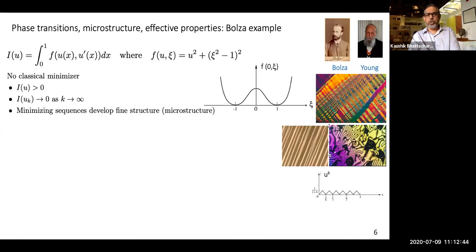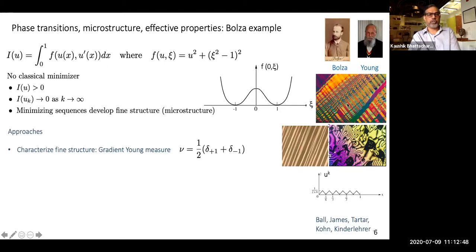And so there are multiple tools you can use, and a lot of them were developed in the context of martensitic phase transitions about 20 to 30 years ago, but we can apply them in many, many different fields. The one is trying to characterize the oscillations. In this sequence, you find that the gradients really take values plus and minus 1. And so the limiting distribution of the gradients is described by a probability measure of 2 Dirac masses, 1 at +1 and 1 at -1.